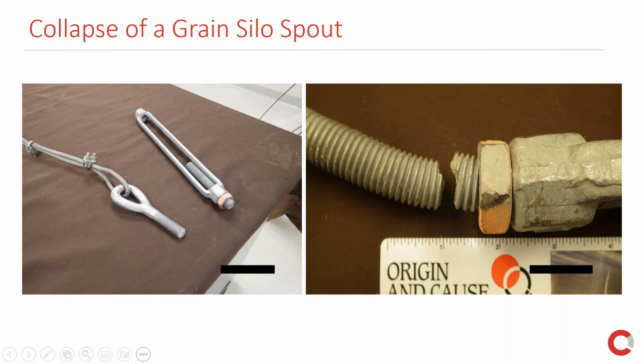During the examination, we also found a turnbuckle, which is shown in this image. And as you can see on the right image, it has been bent and fractured. So after we examined the weld and found the turnbuckle, we said, maybe this would be the cause of the problem. So these turnbuckles are designed to take longitudinal loads. They are not designed to take lateral loads. So this fracture was of interest.